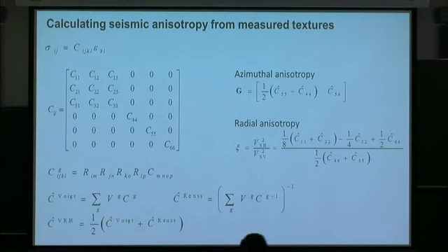After a week that was heavy in sophisticated homogenization techniques, we're relatively crude about this. But we can still look for systematic patterns. So we start with linear elasticity, Hooke's law, and here's that stiffness tensor in Voigt notation. It has all these zeros in it because olivine's orthorhombic, so it has this pattern of orthorhombic symmetry, but all of these values are different, and we can measure this from a different set of tests for one crystal.